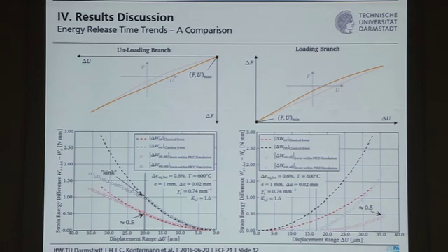And here you see a strain energy difference produced initially, and you observe a kink in these energy trends up to a certain displacement range. And this kink indicates the point at which the crack first closes. And the end value is also 0.5. So now we determined the same effective, so-called effective strain energy differences for the loading as well as for the unloading branch.